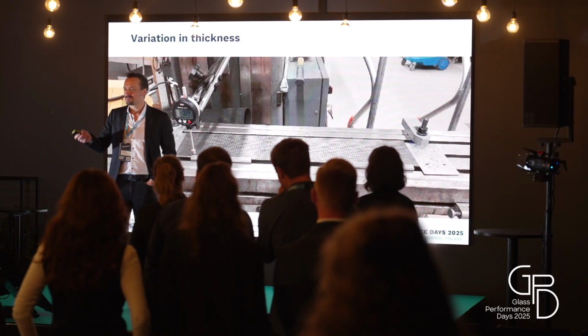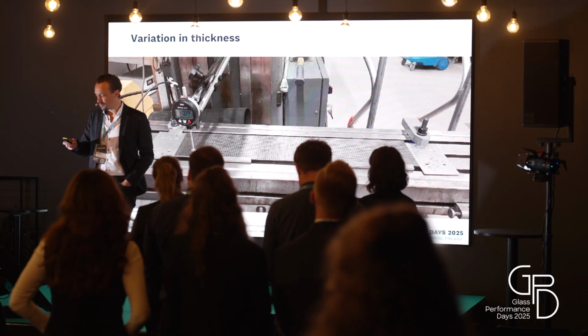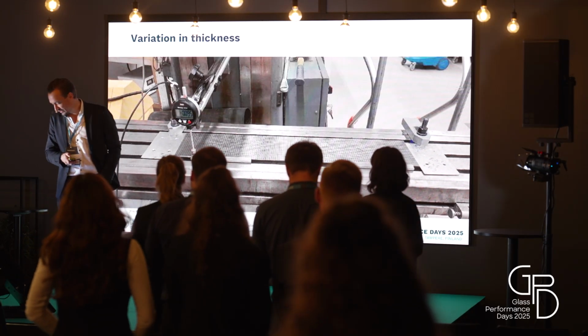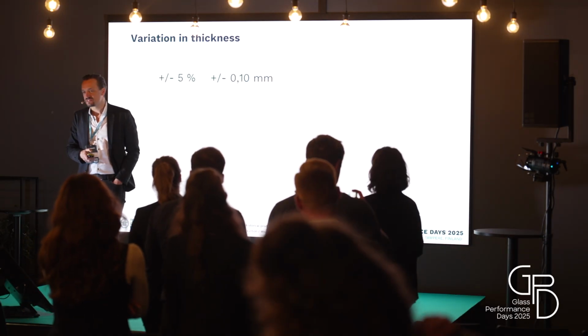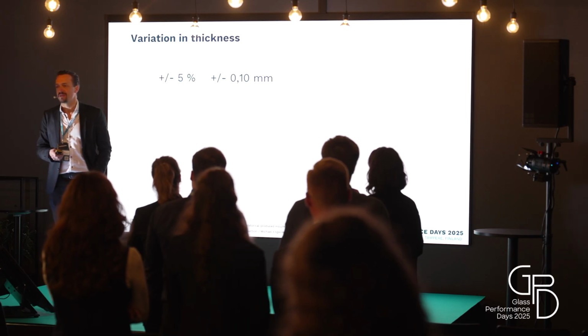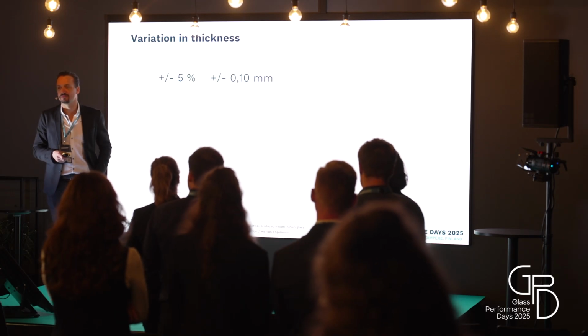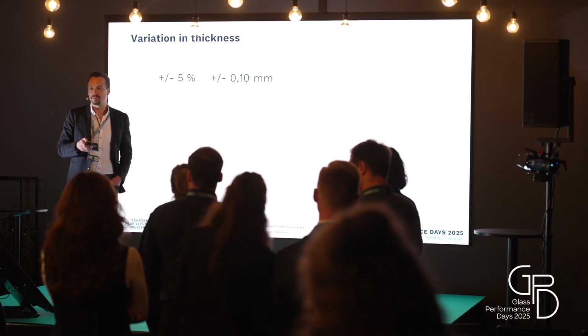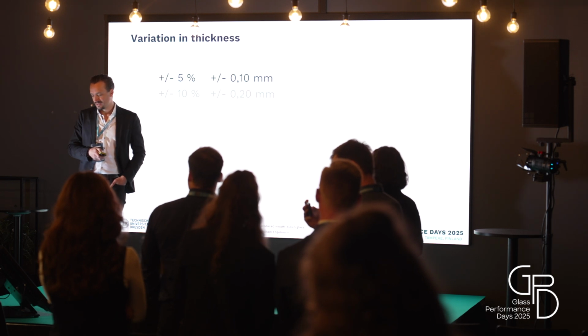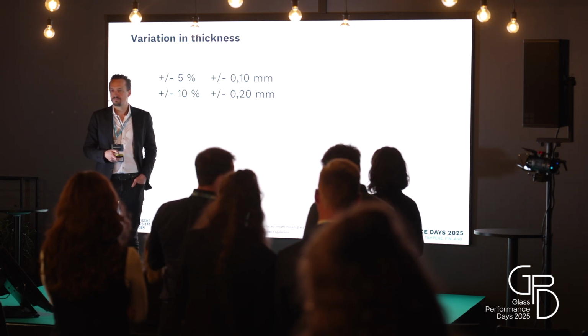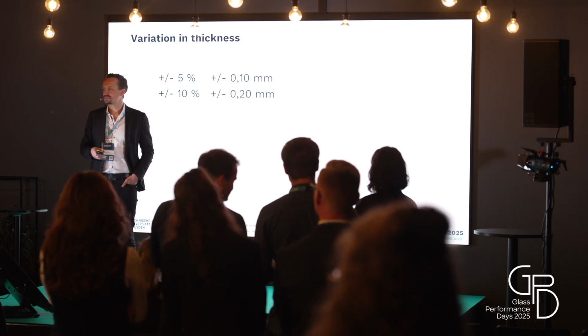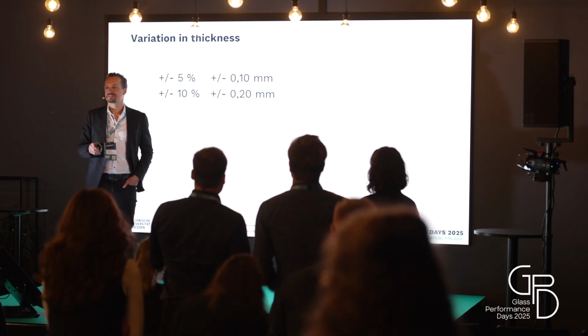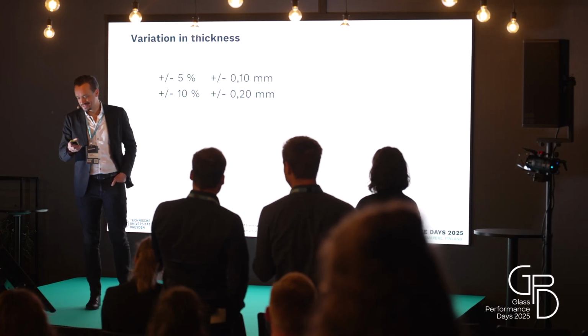Okay, for float glass, it's plus minus 10%, so plus minus 0.2. Please sit down if you think it's plus minus 5% that you actually measure. So plus minus 0.1 millimeter. Nobody? One, okay. Do we actually measure those 10% plus minus? Okay, some people more sitting or getting tired, depends.